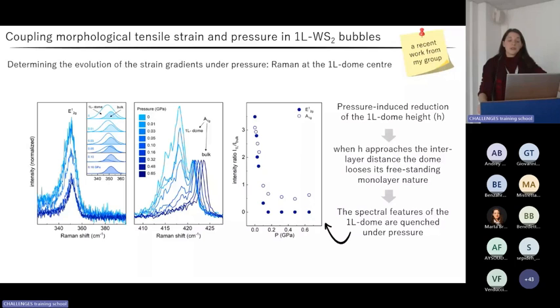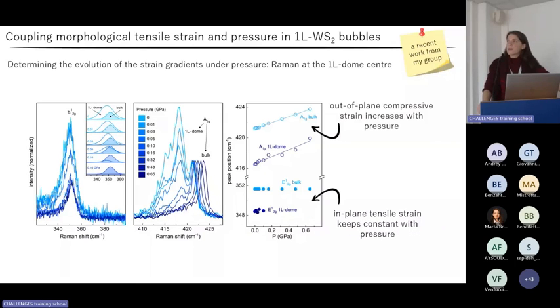Regarding the peak positions, we see that the A1G peaks of both bulk and monolayer dome blueshift under pressure due to the application of compressive strain, while the in-plane E1 2G peaks remain practically unaffected. This may indicate that under the application of pressure, the variation in the out-of-plane strain gradients is much larger compared with the variation of the in-plane strain gradients across the monolayer dome.